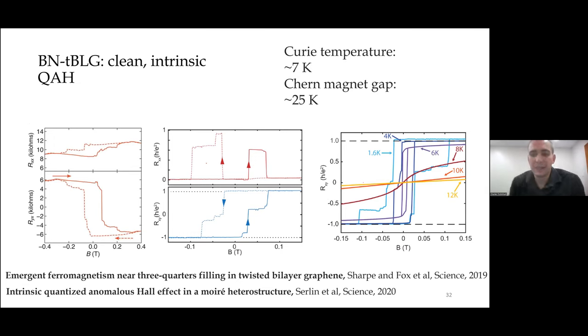This was realized in twisted bilayer graphene by David Goldhaber-Gordon's group at Stanford and also by our group. And in this system, we see quantization all the way up to a couple of Kelvin. And indeed, we see quantization that is limited by the Curie temperature and not by the gap. The Chern magnet's gap is about 25 Kelvin in this system, but the Curie temperature was only about 7 Kelvin. We measure the charge gap with thermal excitation.